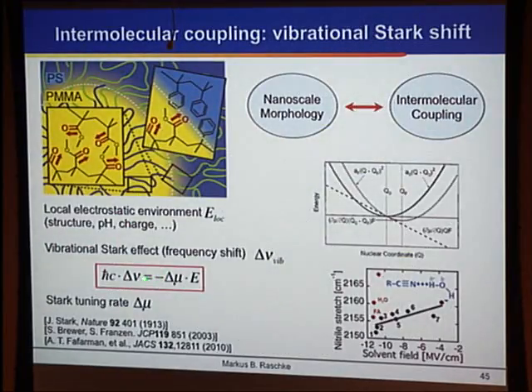The frequency shift, which I mentioned, is a result of that Stark effect. So the Stark tuning rate determines that, which is a calibrated quantity, and then you can actually measure how large the dipole field is, associated, say, with a chemical bond, where in the following sample we're probing this carbonyl oscillator. And these frequency shifts you expect, on the order of a few wave numbers, so a few millielectron volts, actually correspond to relatively large solvent fields.